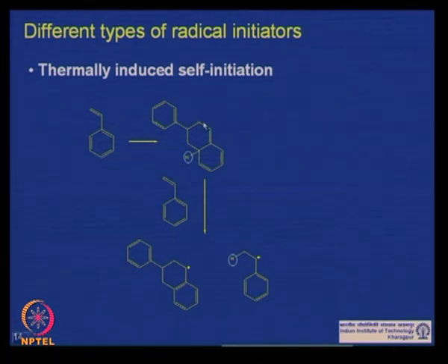this dimerized styrene molecule can react with a third styrene, which abstracts a hydrogen atom, forming two radicals which can individually initiate the chain polymers. This is the proposed mechanism for styrene, which has been proved, but this thermally induced self initiation is not very common, and it is only shown for styrene. So, this is a very specific case for styrene.